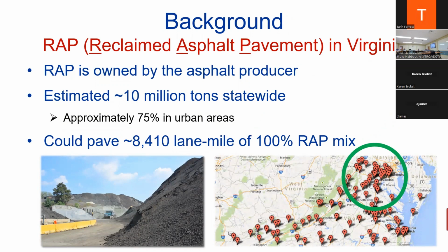So I'm going to talk about reclaimed asphalt pavement, or what's known as RAP. And that's when you mill your existing pavement and then you bring it to the plant and then you create a stockpile of that RAP material. So usually this is owned by the asphalt producer. We estimate around 10 million tons statewide. That's a lot. So if you try to go and just have a layer of 100% RAP mix, it does to you around 8,400 lane miles. That's a lot. So that's a lot of RAP.